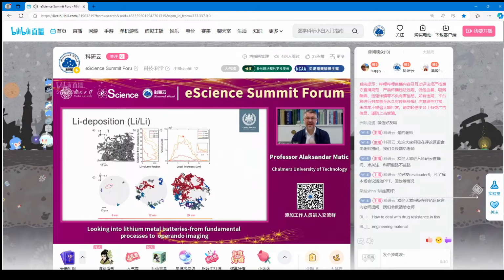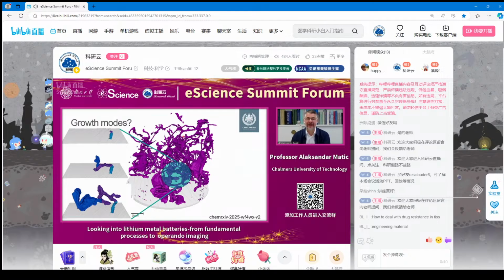So we selected one small piece here, and we could follow the development of this piece. So here is after 6 minutes, you have the first formation, and then you see how this structure then grows. This is after 12 minutes. And then you have a branch here and the second branch going, and then in the end you also form a sheet. But what you can notice is that it is not only tip growth. The structures actually grow everywhere. So you see that this base has actually increased here in size. So the structures grow both at the tips, at the ends, but also from the root.